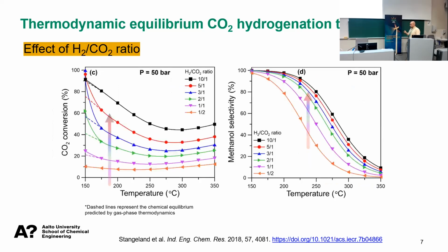Also, we can look at the effect of the hydrogen to CO2 ratio. So in a similar way, I show you the CO2 conversion and the methanol selectivity, but in this case, for 4 different hydrogen to CO2 ratios. So increasing from 0.5 to 10 has a drastic effect on the CO2 conversion and methanol selectivity. So that's why it's very important that the hydrogen that we produce comes from renewable sources, because for this reaction,